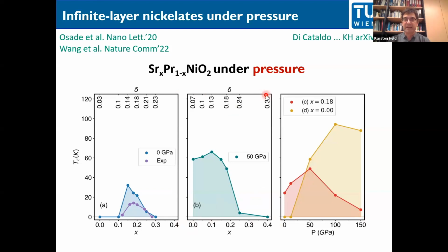We again need a translation to doping. Now 0% strontium doping is 7% hole doping in this x squared minus y squared orbital. And that is enough, together with a larger T, to make the parent compound actually superconducting. So the electron pocket grows with pressure. The doping becomes so much that the parent compound at 50 gigapascal, according to our calculation, gets superconducting too.